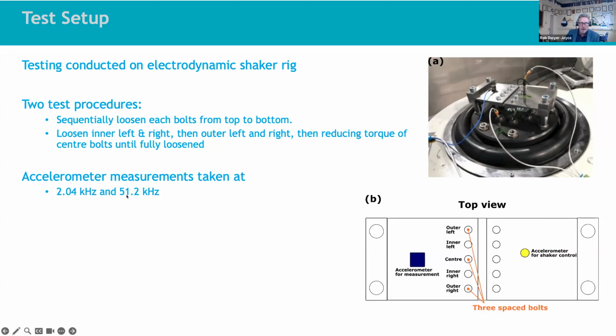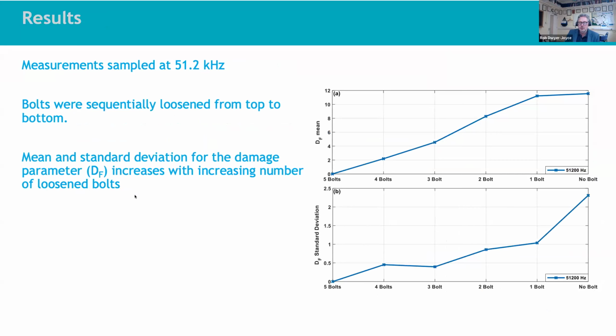using the measurements. We used two kinds of accelerometers, two frequencies, a 2 kilohertz one and a 50 kilohertz accelerometer, to see the effect of the sampling rate on the results. So here's some data from the higher frequency measurement, 50 kilohertz, and you can see that this damage prediction parameter DF very successfully predicts no bolts failing and the effect of increasing the number of bolts which have been fully loosened from top to bottom, 4, 3, 2, 1, and then no bolts. And you can see that it predicts it very well.